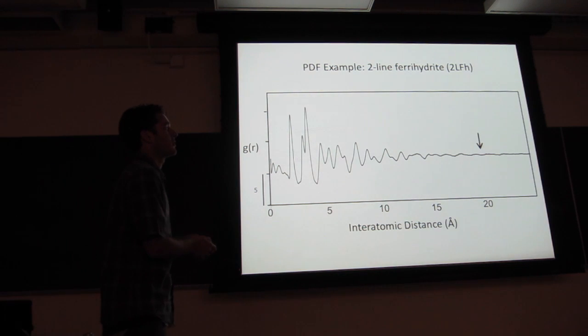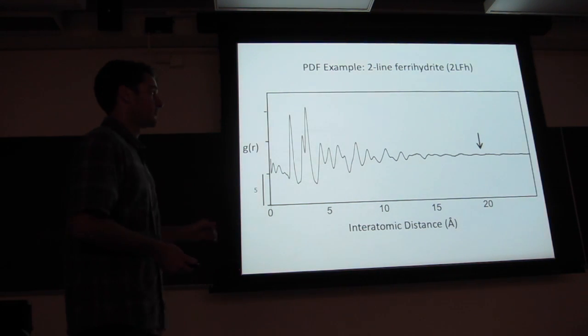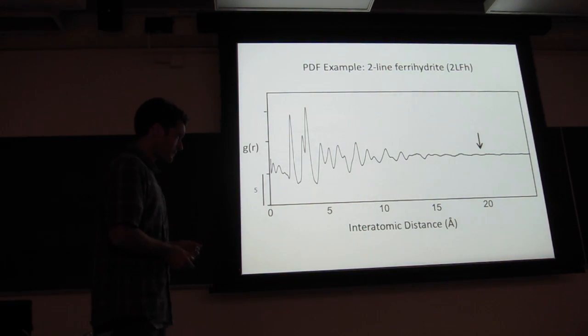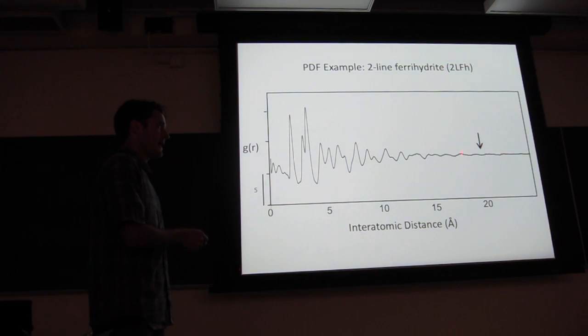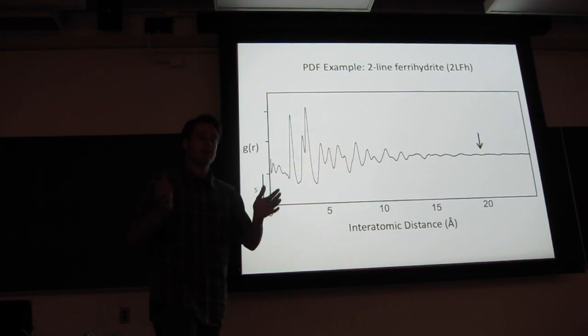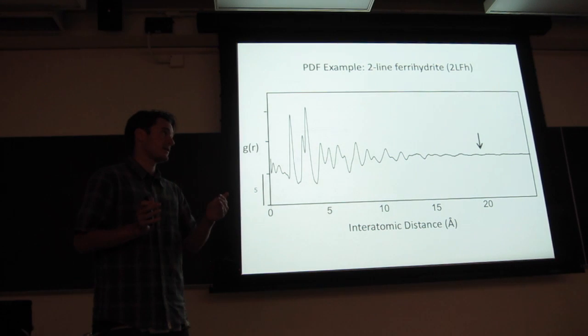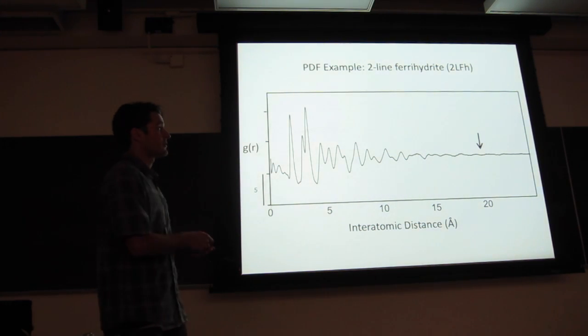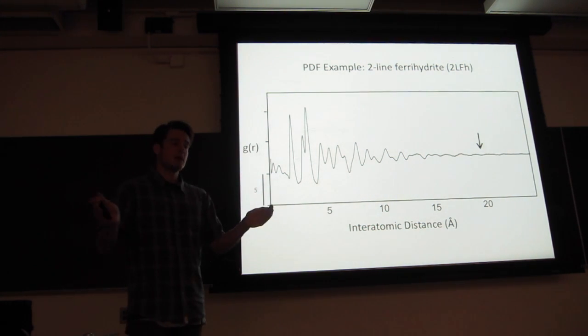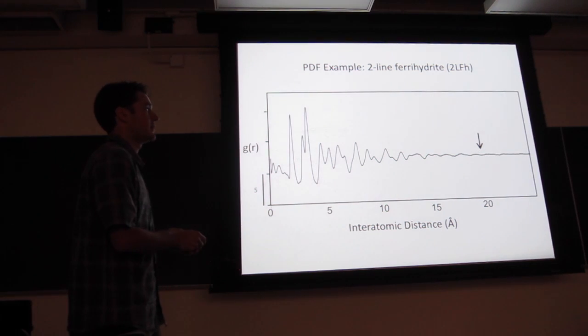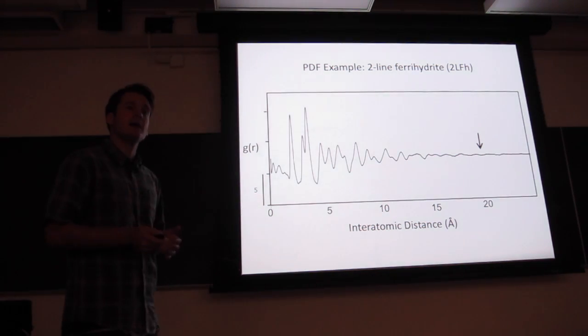And I put an arrow here to highlight another property of the PDF that's really important, at least to my work, is that when these peaks die out, when they decay to zero, that gives you a good approximation for the extent of the particles. That's the crystallite diameter there. Once there's no more peaks, there's no more atoms. So where the peaks die out is an approximation of the size of the particle.